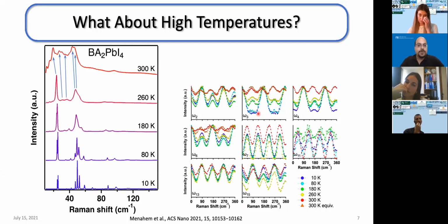So what I did, I followed the peaks along the entire temperature range, in the low frequency, in the low temperature phase and above the phase transition. And I followed their symmetries as well. And I found a great correlation between the modes in the high temperature phase and the low temperature phase, suggesting that this phase transition is indeed mainly dynamic.